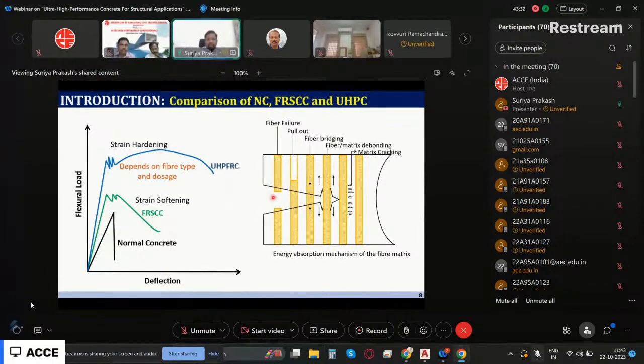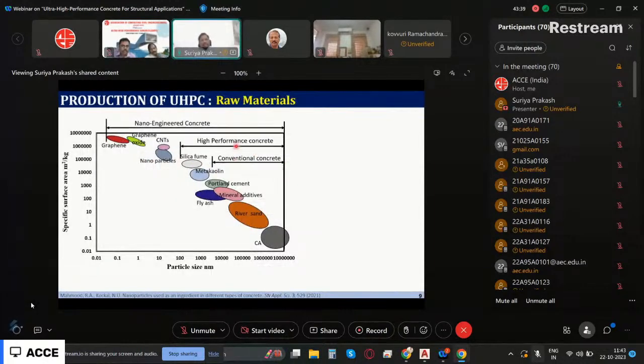Okay. Right. So now in terms of raw materials, in the x-axis I have particle sizes. Let's see what raw materials we are using. Particle sizes are given in nanometer here. Nanometer means 10 to the power of -9, right? So you see here, for a conventional concrete, we are anywhere from 1000 to almost, how many zeros, 7 zeros, 10 to the power of 7 nanometer. Or in other words, up to 10 mm or 20 mm size that we use. This is in log scale. So this is about 1 mm to almost about 10 mm or 20 mm, we can say.